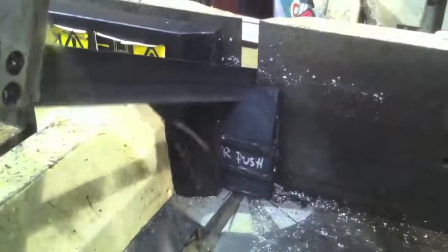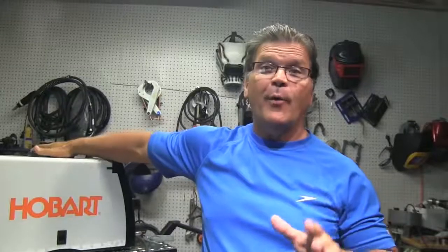And then I cut them using a bandsaw, and then sanded them using around a 120 grit flap disc, and then used a little bit of stainless steel discoloration remover, heat tint remover, to swab etch them to reveal the weld nugget. You can also use naval jelly rust remover. It works pretty good for doing that too, and it's safer. But you can see there's just not a huge difference in the penetration or the bead profiles on any of these welds.